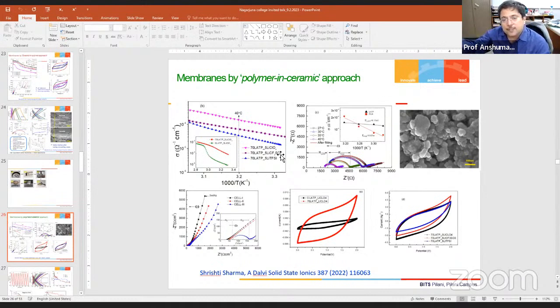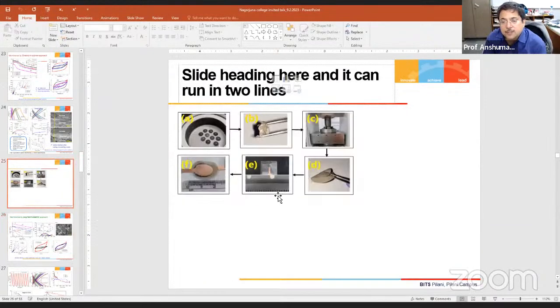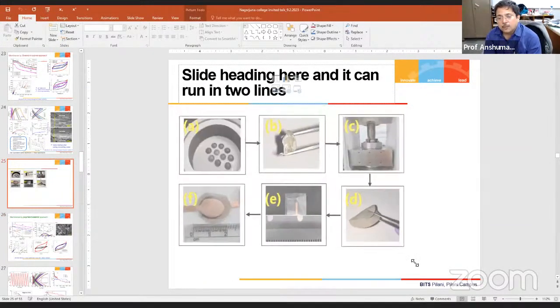So when polymer is added to the ceramic, electrical transport was dramatically very high, because now we have also studied the fundamentals of this. So a lot of work was already done on the fundamental ideas of how the electrical transport is taking place when polymer is added to the ceramic. That means polymer ideally sits between the grains. It is actually acting like a coupling agent between the ceramic grains. So it is facilitating the intergrain transport there. And the conductivity reaches more than 10 to the power minus 4 ohm inverse centimeter inverse in the same polymer film, which was shown here. So this is the ceramic and polymer type of film.